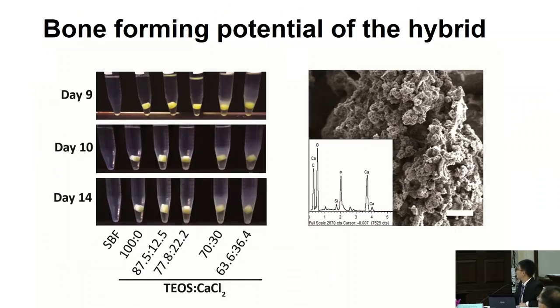And then we tried to prove that our hybrid scaffolds can exhibit bioactivity, or bone forming potential. So we put them in simulated body fluid. It's a fluid that has the same concentration of electrolytes as in the physiological condition. What we found is that after 9 days of submersion, we found this cloudy layer. So we thought that there might be some crystallization of ions.